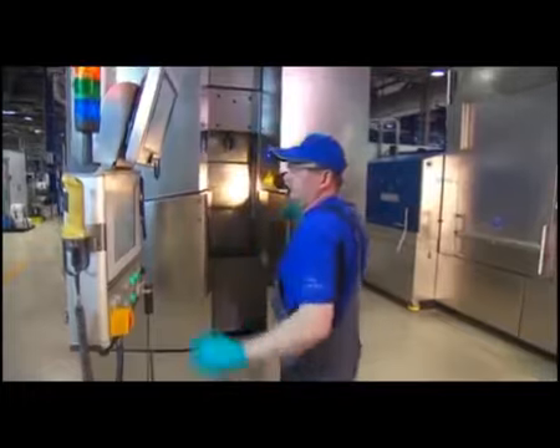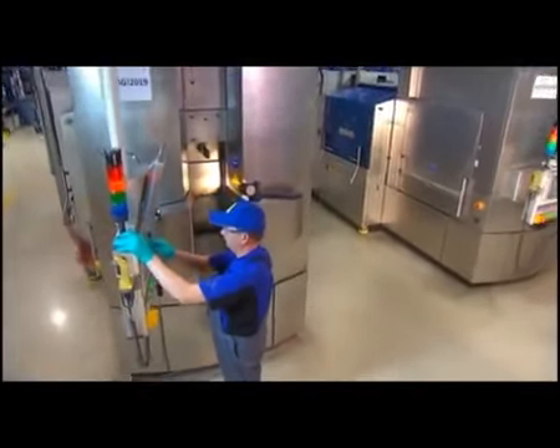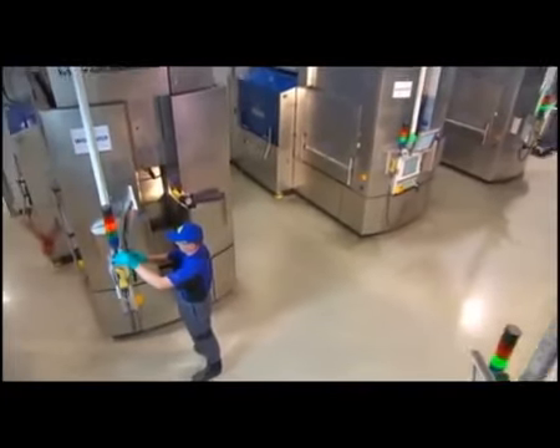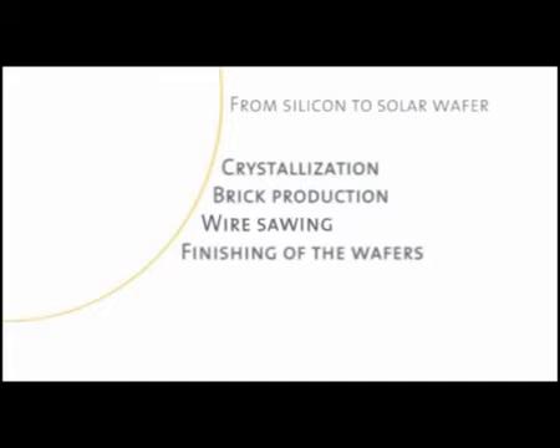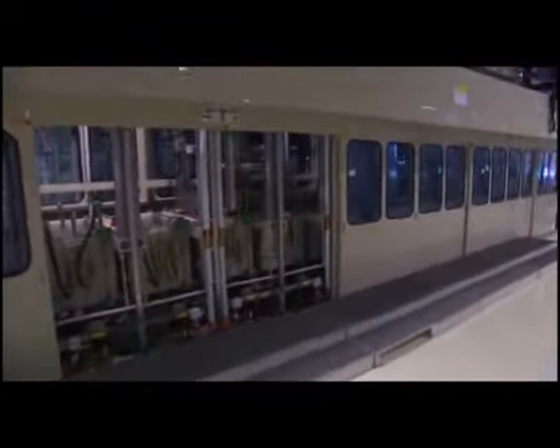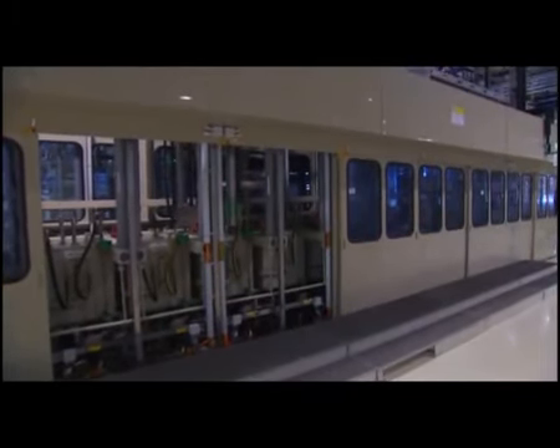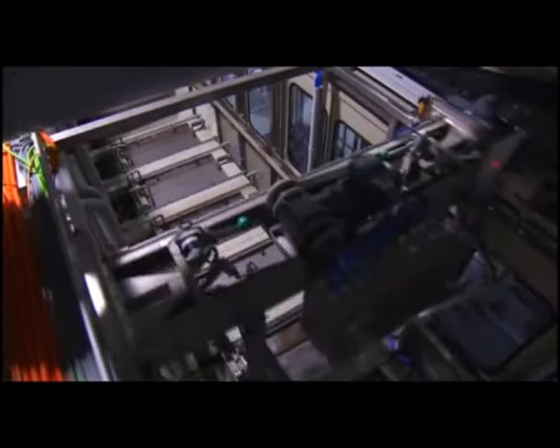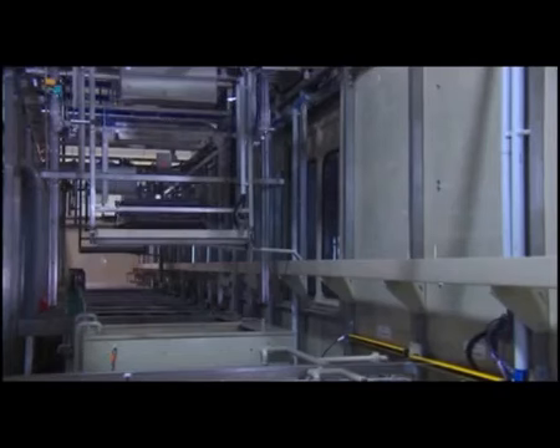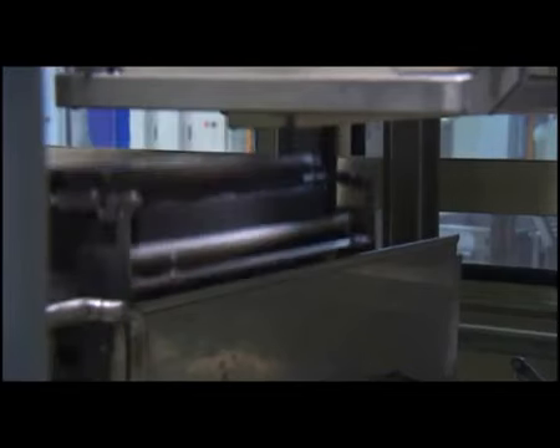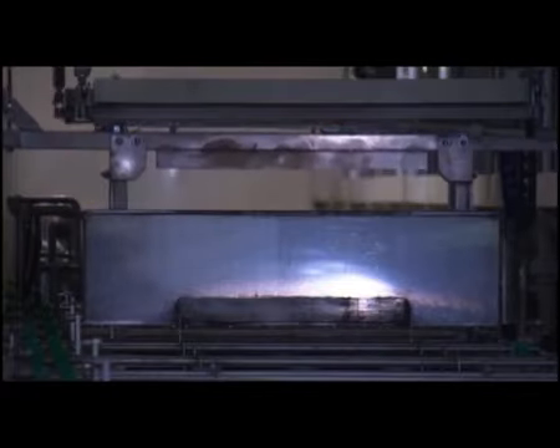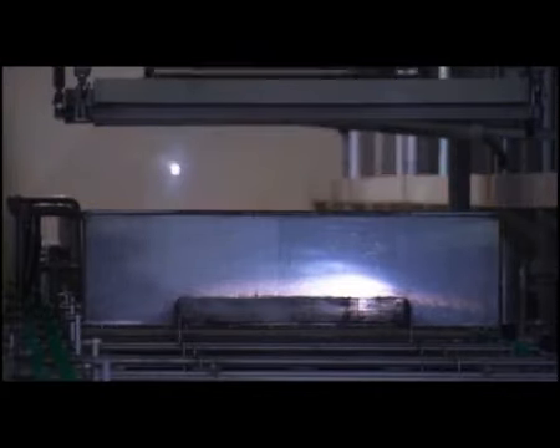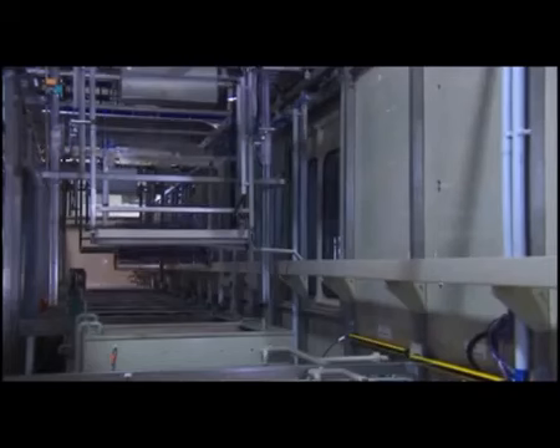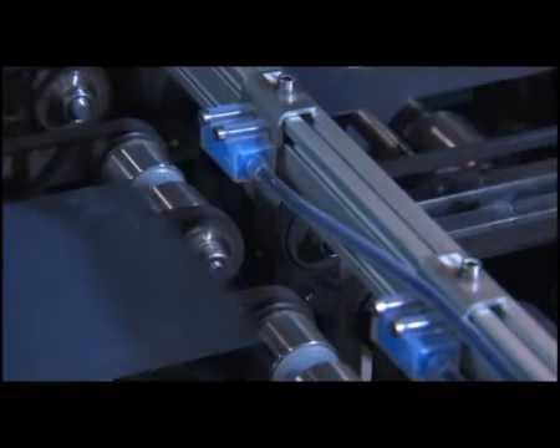As one of the largest photovoltaic companies, Solarworld not only produces wafers for its own solar cell production, but also for sales to customers worldwide. The fourth and last production stage in the manufacture of multicrystalline silicon wafers begins in a large cleaning plant. The sliced bricks, which are bonded to carrier panels, are pre-cleaned in baths to remove all slurry and saw residue. The plant then automatically transfers the bricks to an adhesive removal basin, where the bricks are separated from the carrier panel, resulting in approximately 0.2 mm thin silicon wafers.